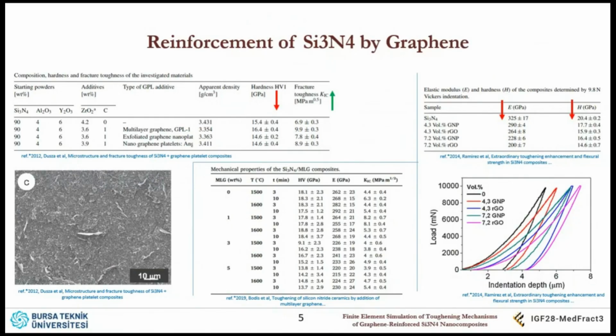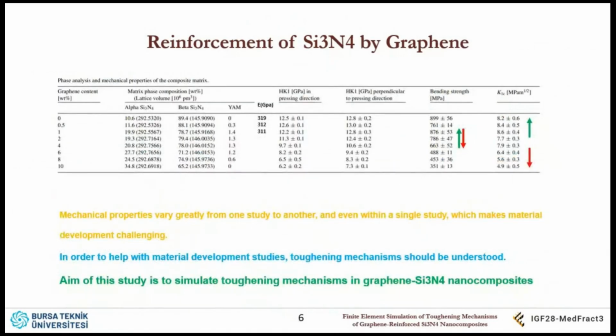This is a regular graphene nanocomposite microstructure. So you can see the dispersion of graphene nanoplatelets. In some studies, many different manufacturing parameters are applied, and you can see too many variations in the results. While you get some improvements and decreases in the bending strength, likewise you get some improvements and some degradations in toughness. So the mechanical properties vary greatly from one study to another. And this makes material development studies a bit challenging.